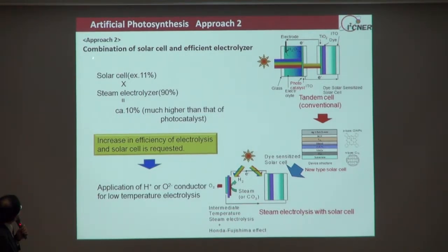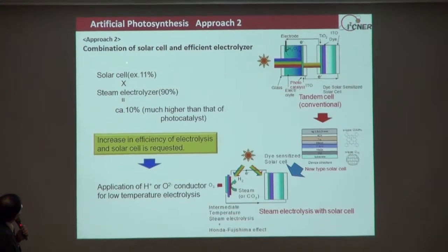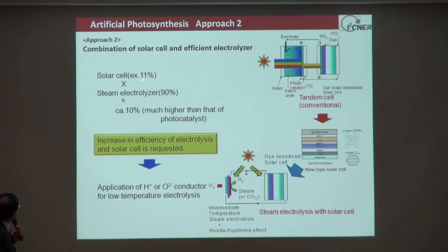And the next approach is the combination of solar light and efficient electrolyzers. This is more engineering-like, because the solar cell has already been commercialized, and even in these buildings we can use the solar cells. But the current solar cell consists of silicon and consumes a lot of energy for production. Therefore, we focus on the organic solar cell, which does not require high energies for production. But in the case of the organic cells, the conversion efficiency is not so high. Therefore, we increase the conversion efficiency of the organic type solar cell to, for example, 11%. And then we apply it to the steam electrolyzers.